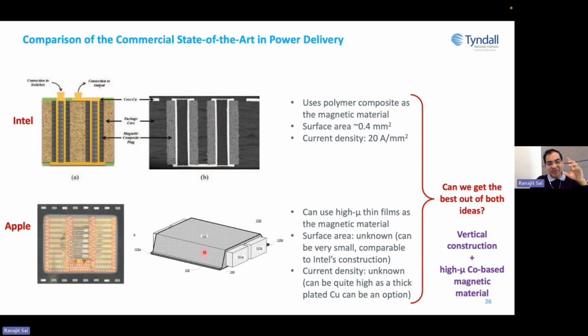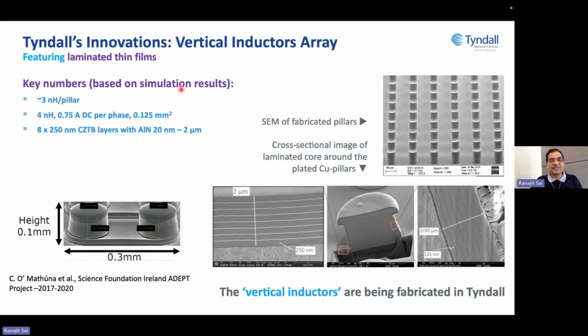The question is, can we make a vertical pillar with a thin film around it? Then in a very small pillar we can get a significant amount of permeability, because the permeability is almost some 20 times more. That brought us to this vertical inductor concept, and it is now patented by Tyndall. What you are seeing is just a 100 micron tall pillar, and those copper pillars are connected underneath. So this is basically one inductor connected to another inductor in series, and then they are 2 terminals. Now, if you deposit magnetic material around it, the magnetic material will look like this.